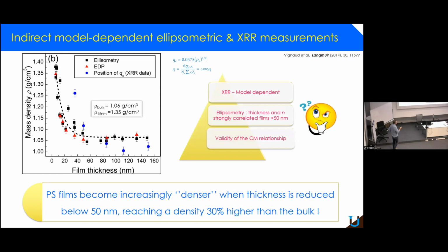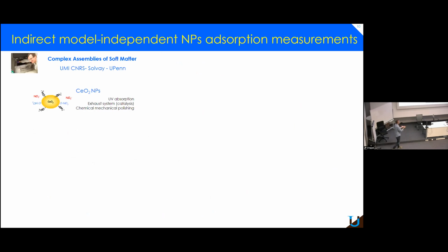But obviously, as many people told us, it was very complicated to publish. X-ray reflectivity is a model-dependent type of experiment. Ellipsometry is complicated also because you cannot really decouple the refractive index and the thickness, especially when you're working below 50 nanometers. And we didn't know if the Clausius-Mossotti relationship was really valid at that dimension. So we decided to go further and push forward something different, to assess at least directly that the density was varying in polymer films.